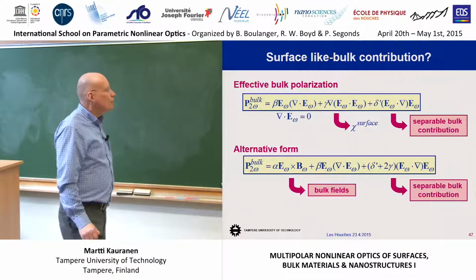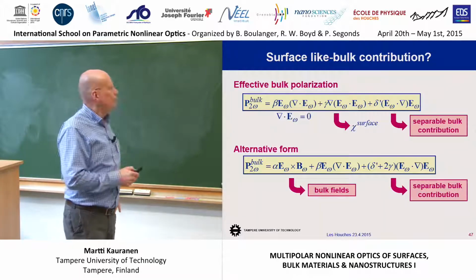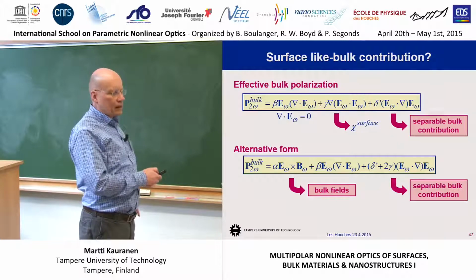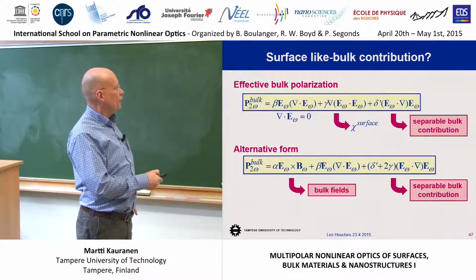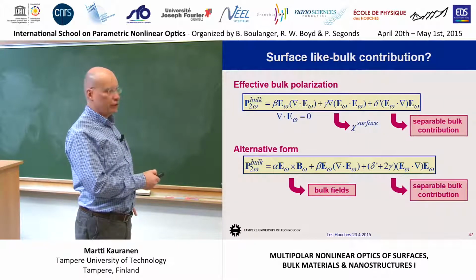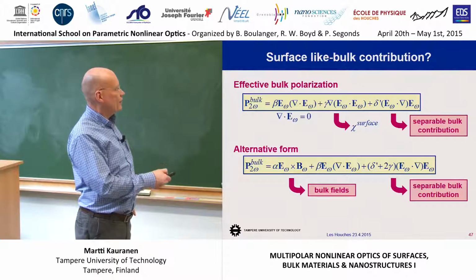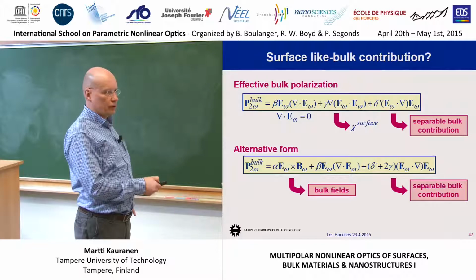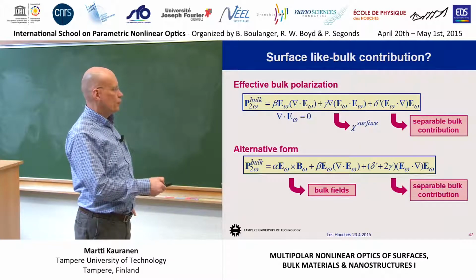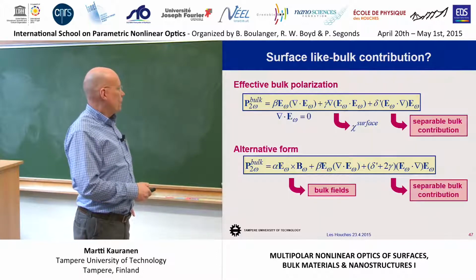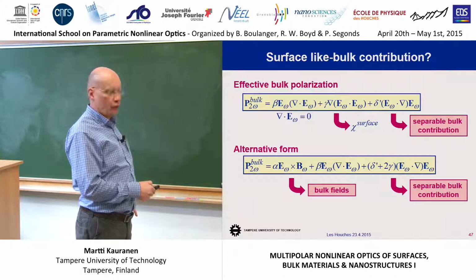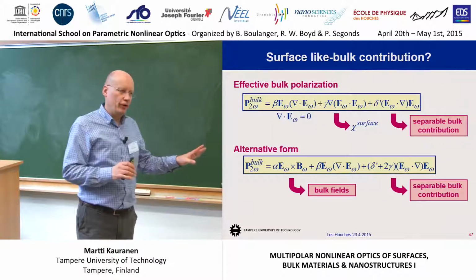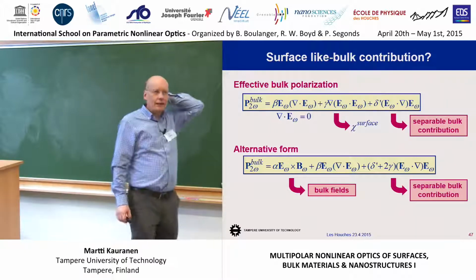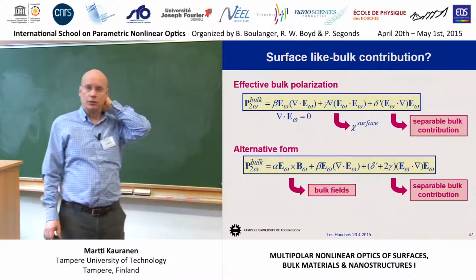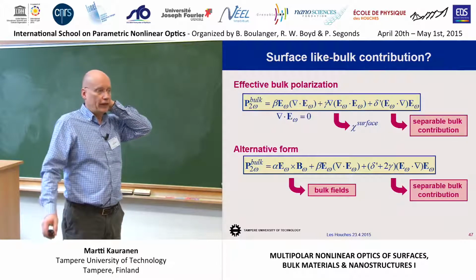Okay. So the funny thing is that what we have now done here is that we have played a mathematical trick which completely removes this part out of the expression, which behaves as an effective surface contribution. We know that this functional form here represents a separate bulk contribution. So we can measure it. And furthermore, this alpha here depends on the bulk fields, the electric component and the magnetic component. So there's something very, very funny going on here. So the big question is, does it even make sense to try to separate the surface and bulk contributions? I don't know at this point.